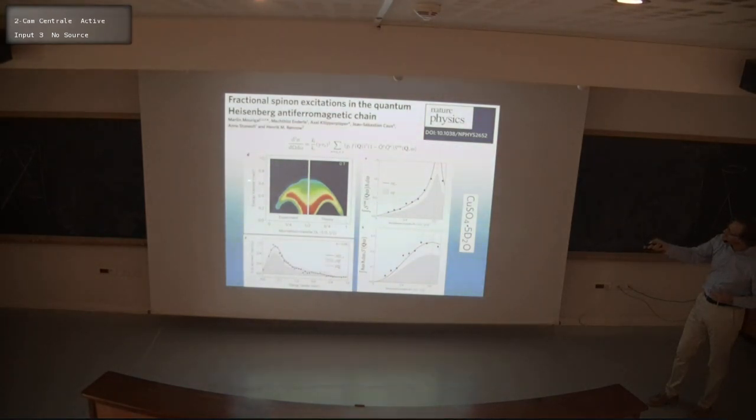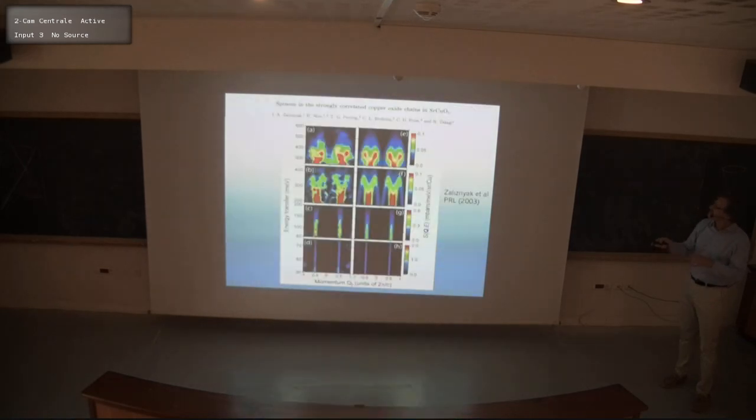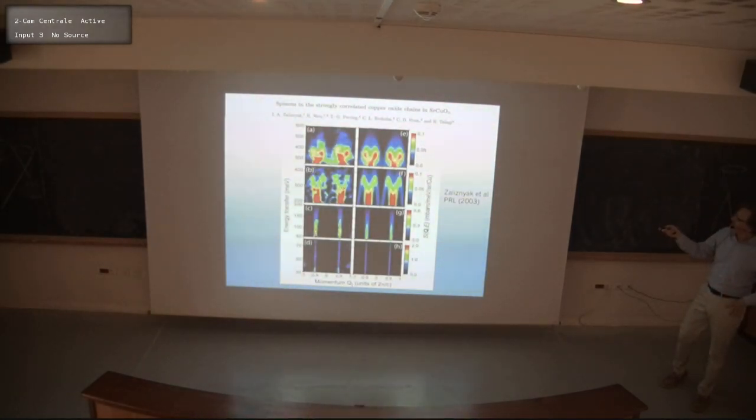Here we were talking about things down around 0.5 millielectron volts, so this is like 5 Kelvin, so it's really low temperature physics. I think this is probably done in a dilution fridge and so on. Then you go to this compound, and actually the energy scale instead is 0.5 electron volt for these excitations. So it's a different exchange process. The energy scale is much larger. The physics is the same, actually.